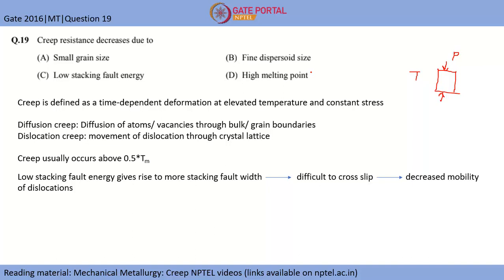Creep usually occurs above 0.5 of the melting point. This is because we are talking about diffusion of atoms and vacancies, and diffusion is a temperature accelerated process. At higher temperature diffusion will be faster, hence higher temperature is required for vacancies and atoms to move. If we consider a higher melting point, we will require a higher temperature to cause the same creep in a material. Hence the creep resistance will increase if we have a high melting point.